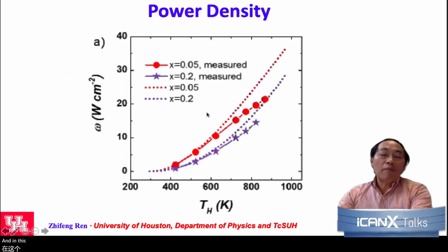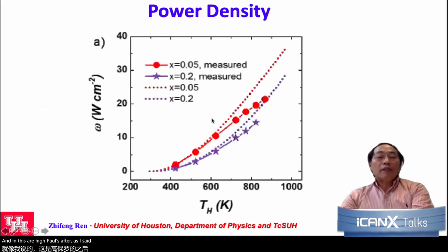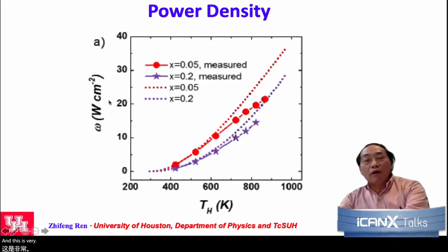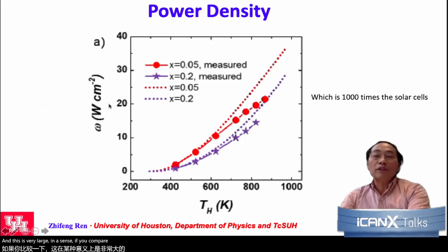And this high power factor, as I said, is based on the individual measurement. And we indeed also measured the actual power density based on the power factor, and also calculated it. This power density is about 20 watts per square centimeter. And this is very large if you compare with solar photovoltaic cells, where the power density is only about 0.02 watts per square centimeter. That's about 1,000 times lower than thermoelectrics.